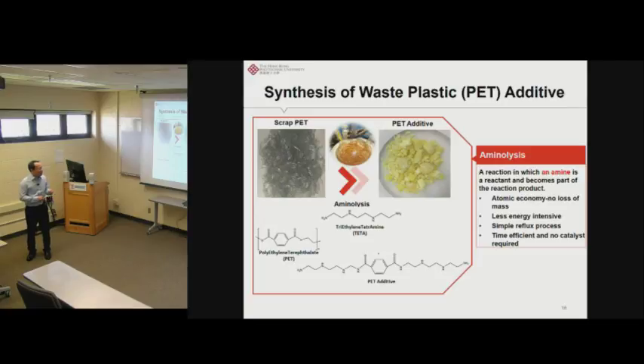Also, the process is quite simple. We just need to put the two materials together into some container. And finally, it is relatively time efficient, and we don't need to add any additional catalyst. The reaction usually just takes 6 hours to complete. Because of these reasons, we selected this chemical treatment process.